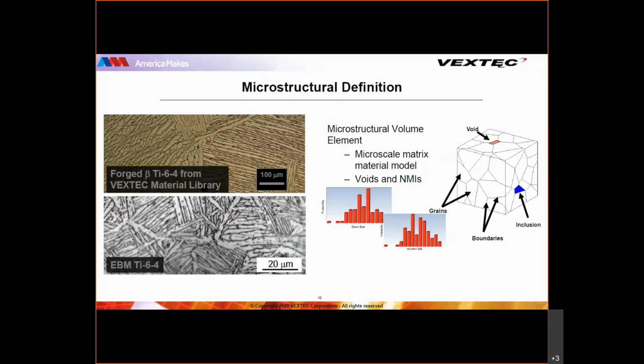The difference is that there can be differences in grain sizes. A lot of times the grain size is an order of magnitude smaller because of the quick cooling rates of the EBM Ti-6-4, but also the effect of defects. And there can be a trapped gas, porosity, unmelt particle inclusions. And if you can identify and capture those and put those into your model and use as a baseline the forged Ti-6-4, we've been able to model the AM Ti-6-4. And this is an example that I'm going to hand back to Mike, and he's going to actually show this, how we can go about doing this.